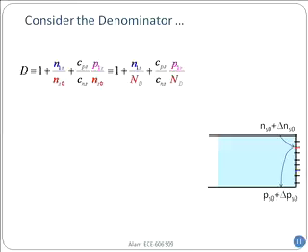Okay. Now, do you see the substitution I have made? NS0 in the extrinsic region. Remember that extrinsic region? Freeze out, extrinsic, intrinsic region. So I have replaced in the extrinsic region NS0 with N sub D. So that's a constant. The only thing I have to worry about now, everything I know now, somehow I have to take care of N S1 and P S1.